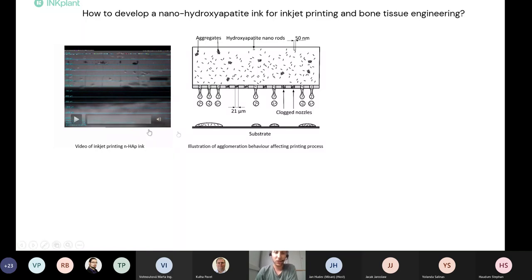I tried to illustrate the importance of being able to control the agglomeration behavior in an inkjet printing process, especially for our nanohydroxyapatite ink. As I mentioned before, we're talking about nozzle diameters of about 21 micrometers. So it's really important to prevent nanoparticles from agglomerating prior to printing, because agglomerations can clog the printhead, and usually this is an irreversible process. When one nozzle is clogged, the printhead is damaged.